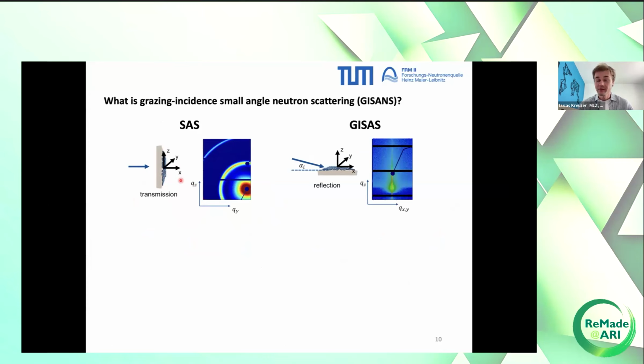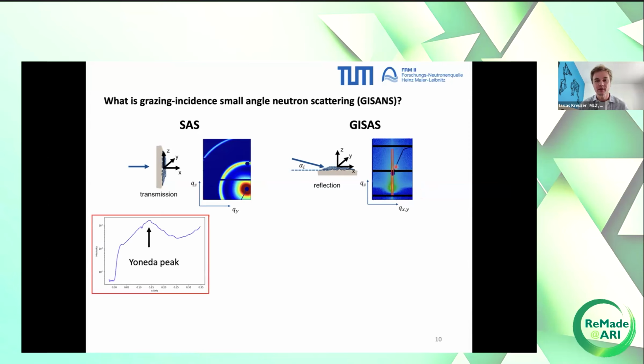But if you have a very thin film and you don't have a lot of scattering volume, you do a little trick and rotate it by 90 degrees and illuminate the film under a grazing incidence. Then you have a certain footprint and a larger illuminated area, and you get a better signal, better statistics. But then also your scattering image looks different. For example, like this. And what you can do now is, for example, do a horizontal line cut at a fixed QY. Or this is a vertical line cut, sorry, at a fixed QY position,